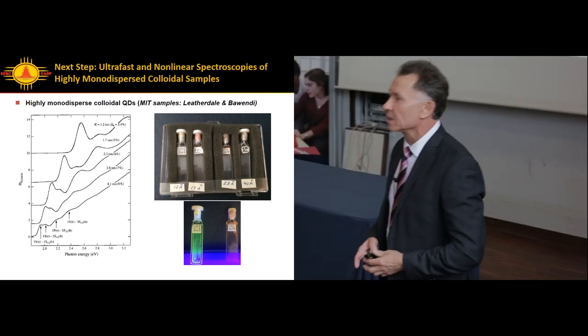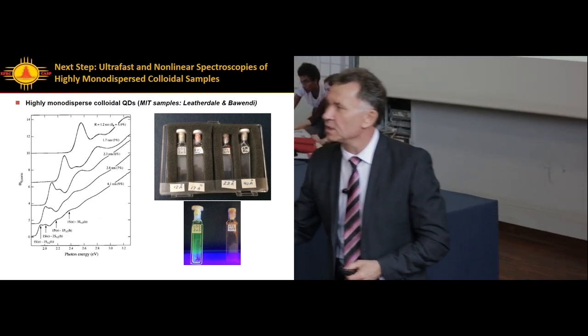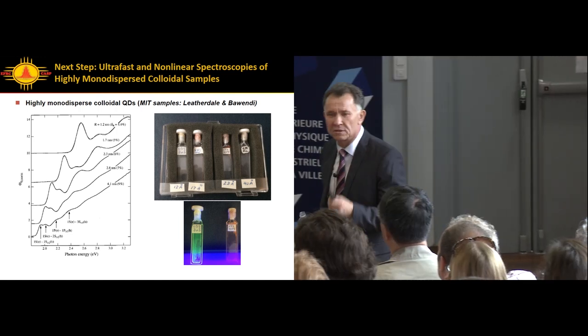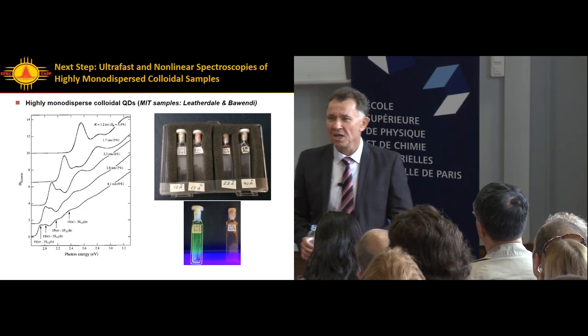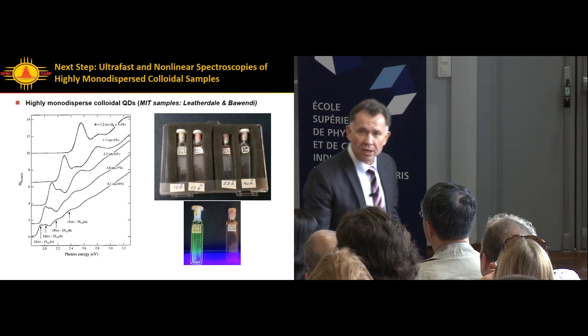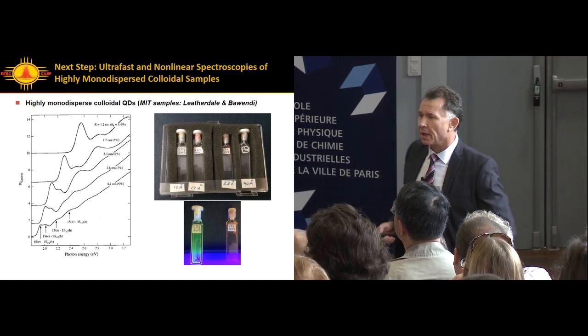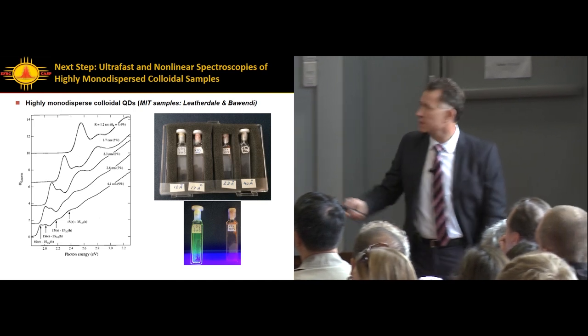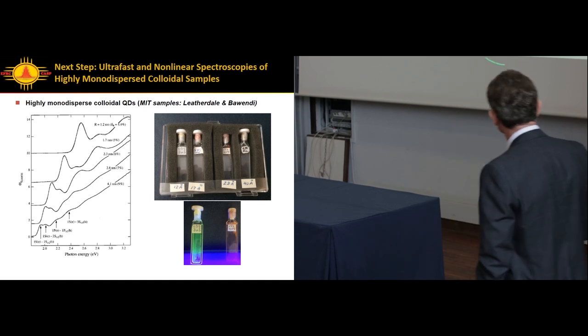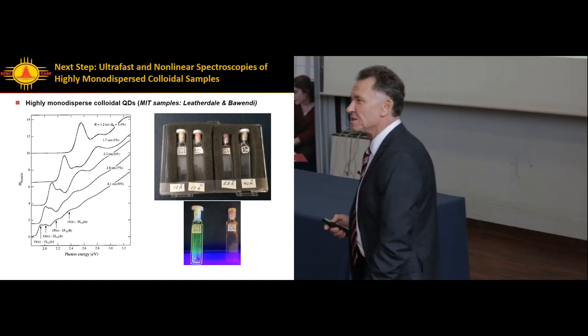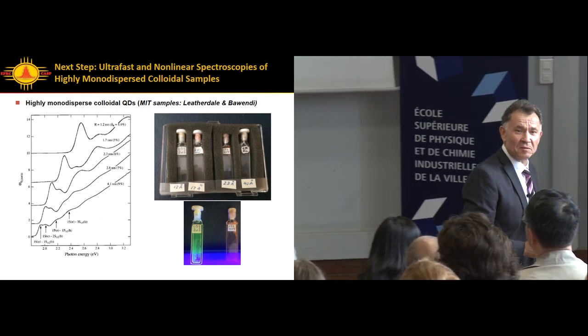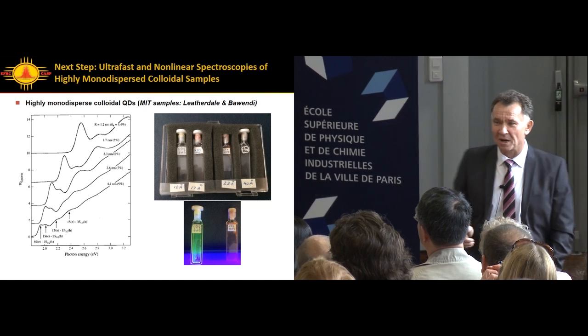We looked at two sizes and saw a certain size effect. The initial time constant changes depending on the size from about two nanoseconds to a few hundred picoseconds for smaller sizes. That was not sufficient to ensure the exact size dependence. This is where colloidal samples with perfectly defined sizes became extremely useful to evaluate the size-dependent trend. Physics of quantum dots is about size-dependent trends. Really grateful to Moungi, he's in the audience.